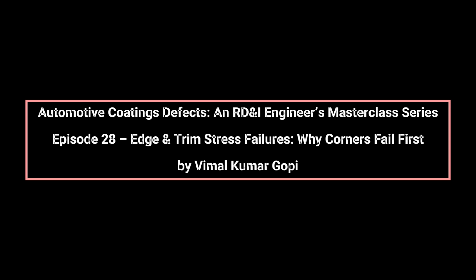Edge and trim stress failures illustrate the principle that coatings are dynamic, multi-layered systems that interact with substrate geometry, thermal cycles, mechanical movement, and environmental exposure. Optimizing coverage, crosslink density, curing, and additive strategy for these worst-case areas ensures that the coating survives its intended life while maintaining appearance and corrosion protection.